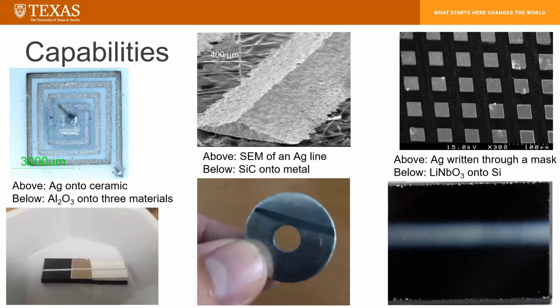So the capabilities of our process, the top row is all silver onto various materials. On the left, it's a small RF antenna of silver written onto a hard ceramic. And in the middle, on the top, we see an SEM line of silver onto a stub. And this shows the typical cross-section of a film, which is going to be roughly Gaussian distribution that you can raster along an axis to produce a film and along 2 axes to produce a thick film.